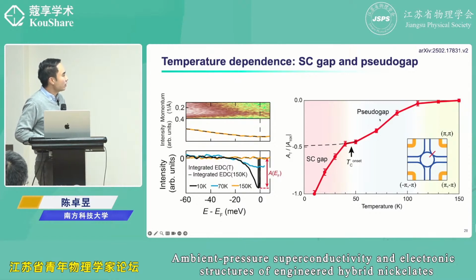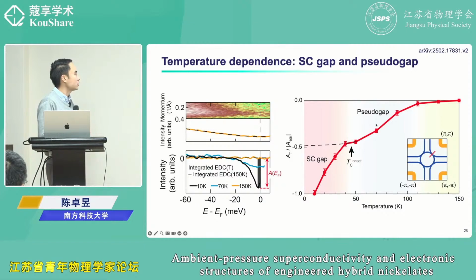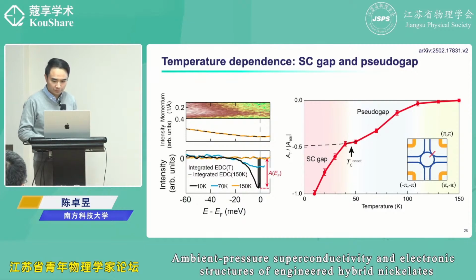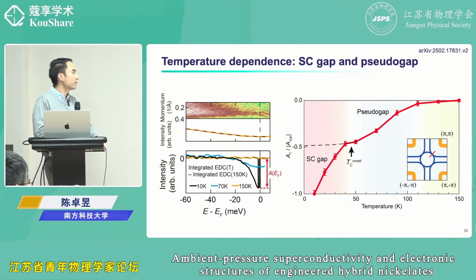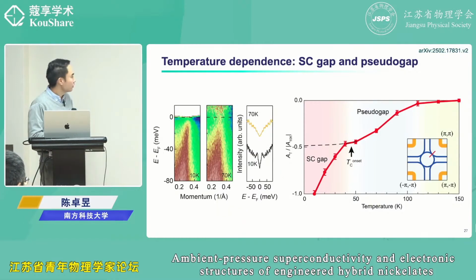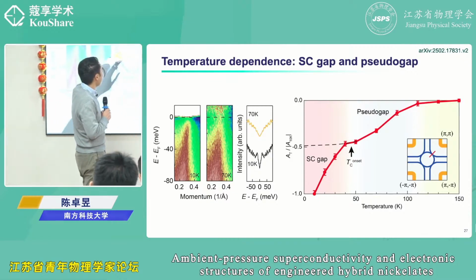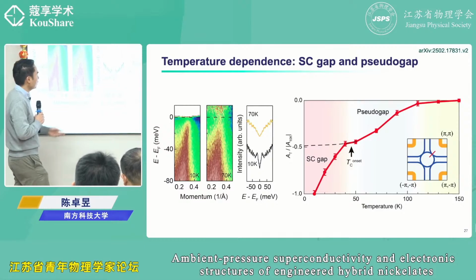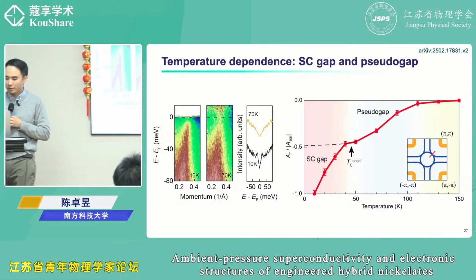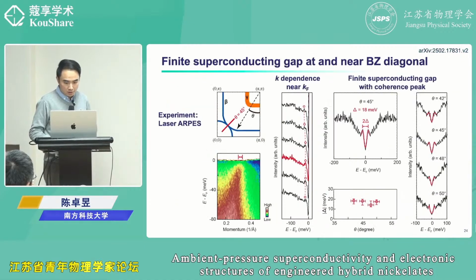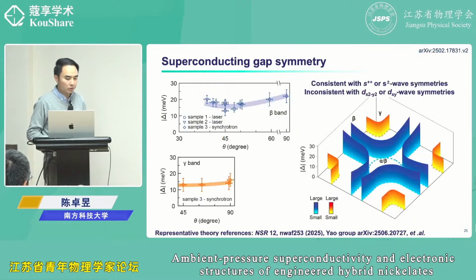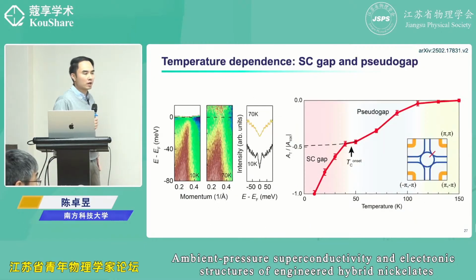But for this gap without a coherence peak, it's hard to say what it is. We can just say it's a pseudogap. But whether it's the same as the pseudogap in cuprates, we are not sure. Energy scale, I guess it's not well defined, but about 20. The superconducting gap is close to 20, so it's slightly larger. So 30, 40, that kind of scale.